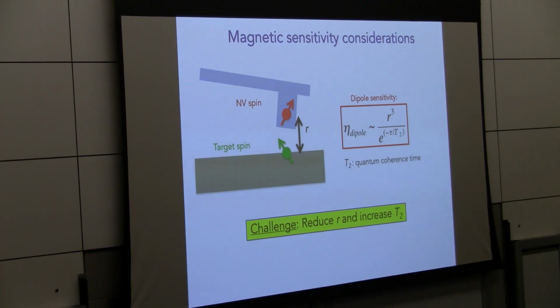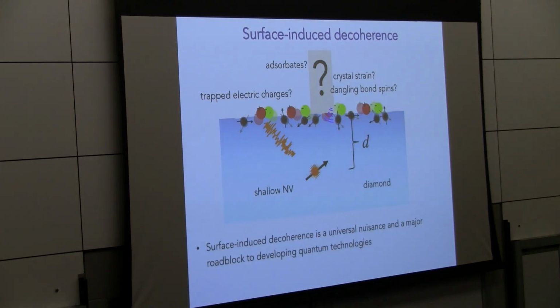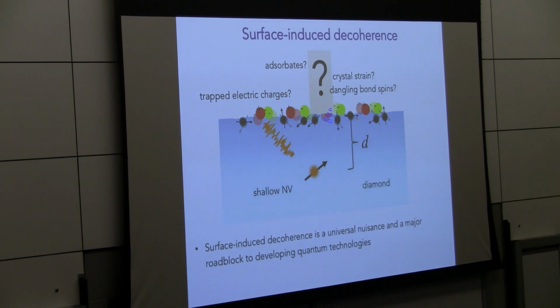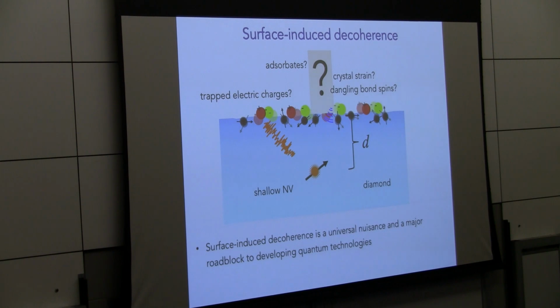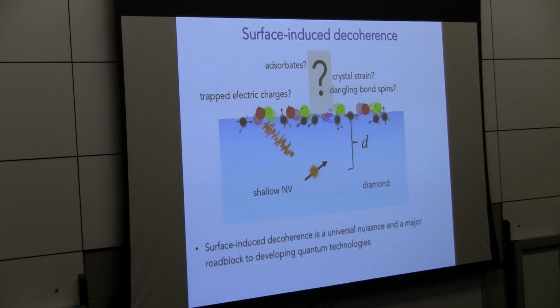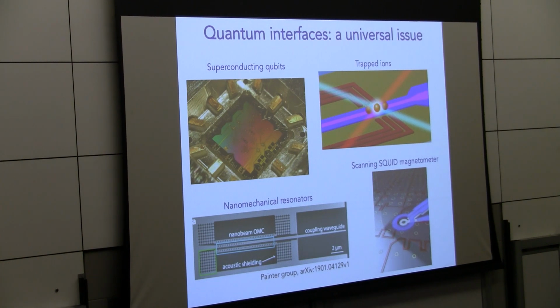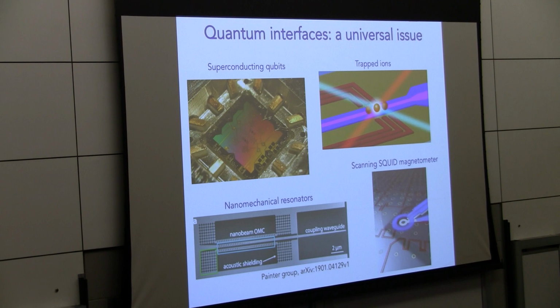But that's a challenge because anytime you come near a surface, things become a bit uncontrolled. The really protected diamond lattice is no longer there, and we have some uncontrolled surfaces. That uncontrolled nature could come in the form of trapped electric charges, adsorbents, crystal strain, dangling bond spins. There's a myriad of uncontrolled elements, especially when we're working in air, that can occur. This is an issue for NV centers, not just for sensing, but also for any experiments where one wants to couple the NV center's quantum degree of freedom to, say, a phonon or a photon, which often requires nanostructured devices, which necessitate surfaces nearby. And not just for NV centers, but probably the main limitation to developing a lot of quantum systems is these interfaces.